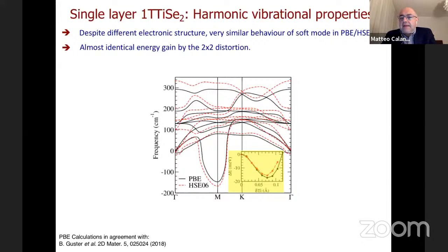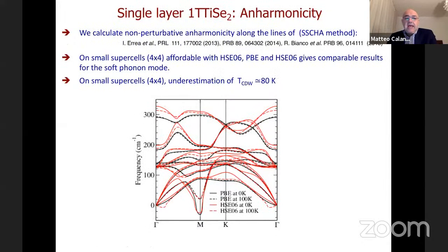It means that the phonon dispersion, for what concerns the unstable modes, not all the modes, because at high energy there are differences, behaves as if it doesn't know about the electronic structure, and the system doesn't know about the band overlap between titanium D and selenium. However, one can try to calculate the anharmonic correction to the spectra. This is difficult because the anharmonicity is non-perturbative. Here you have a negative phonon, a very strong imaginary phonon, and the anharmonic correction is of the same order as the phonon frequency itself. So you are in the deeply anharmonic regime.